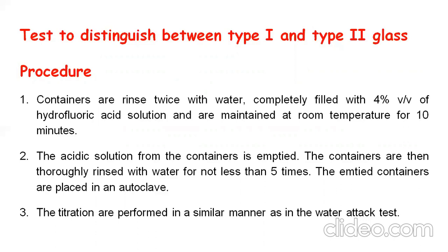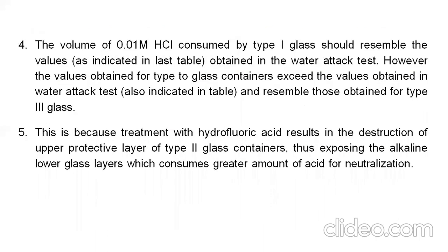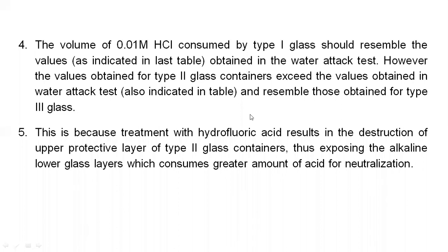The containers are then thoroughly rinsed with water not less than 5 times. The emptied containers are placed in an autoclave. The titrations are performed in a similar manner as in the water attack test. The volume of 0.01 molar HCl consumed by type 1 glass should resemble the value indicated in the glass table obtained in the water attack